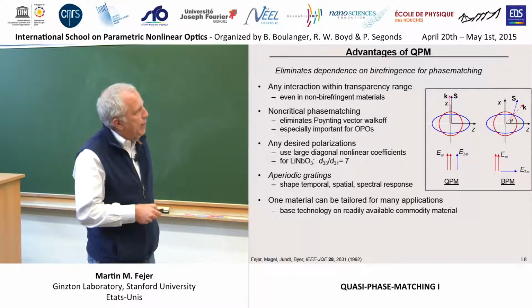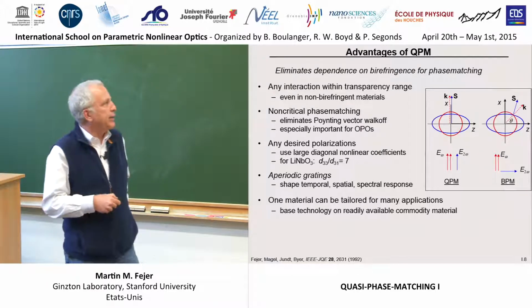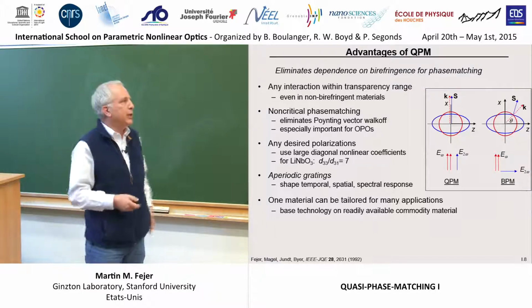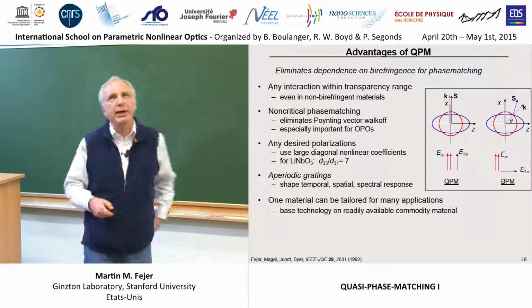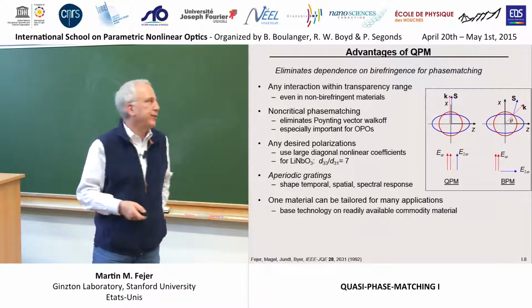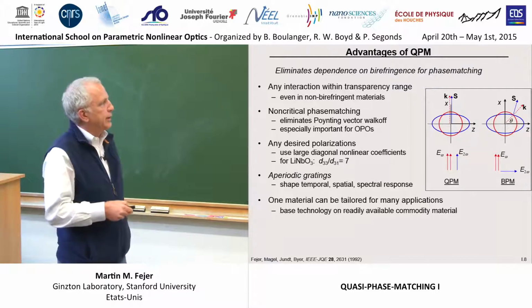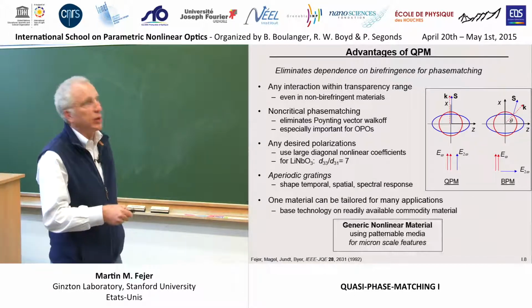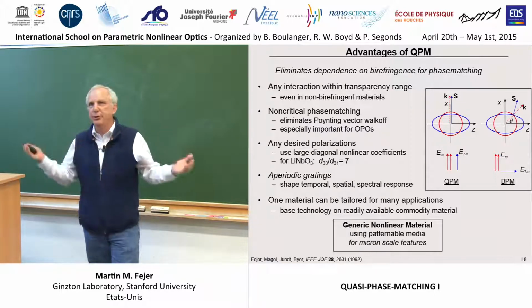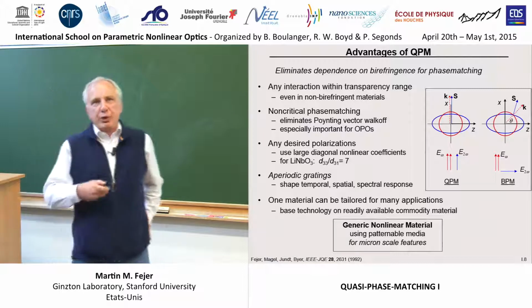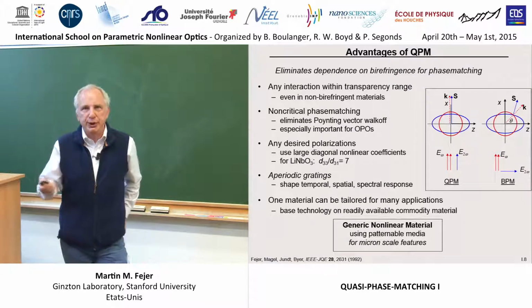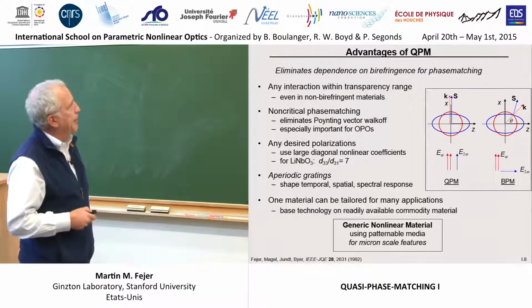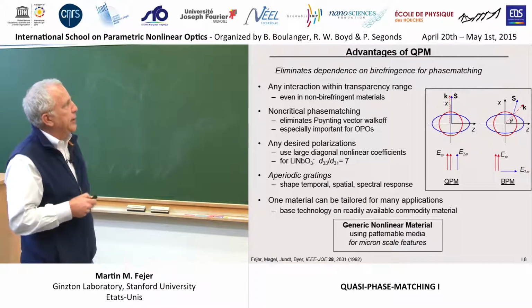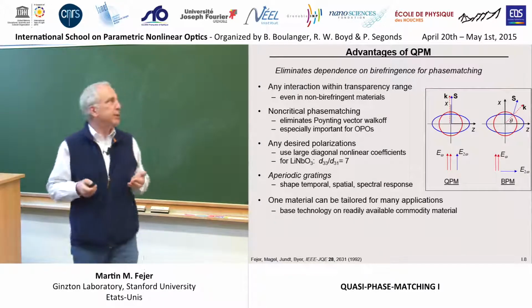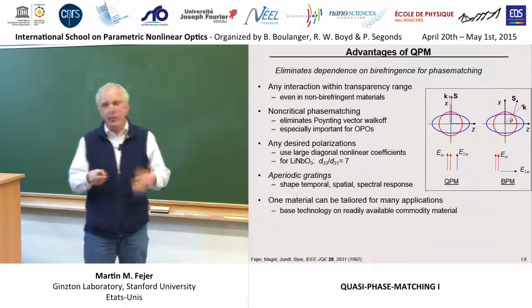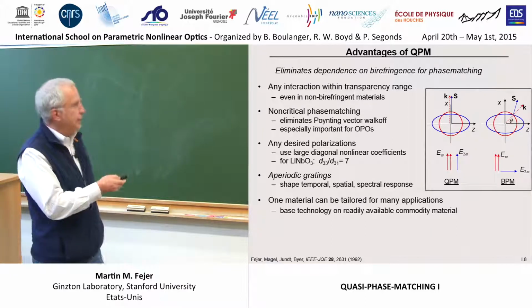And you can use parallel polarized radiation, which means you have access to the diagonal nonlinear tensor coefficients. Those are often much larger than the off-diagonal ones that you need to couple orthogonally polarized waves for birefringent phase matching. In the case of lithium niobate, the nonlinear coefficient for this case is 7 times larger than the one for that case, and the efficiency goes with the square of that number, so that leads to those much reduced, for example, parametric oscillator thresholds that Majid was talking about earlier today. In addition, you can now operate essentially any interaction within the transparency range of the material, as opposed to the ones where you happen to have the right balance of dispersion and birefringence.